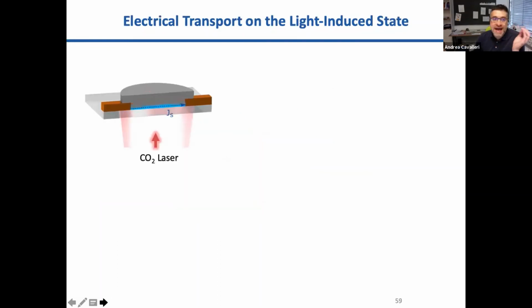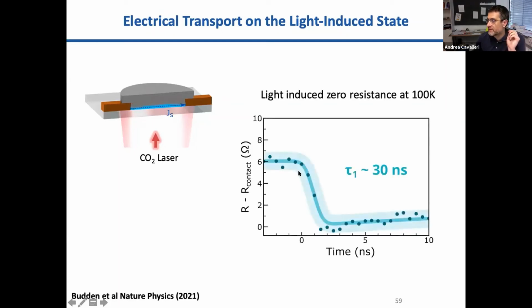So things that we're doing now, of course, now that we have longer-lived superconducting-like states, we have measured resistivity using 2 probes, and we could show that at least with 2 terminal measurements, which require some calibration, the resistivity of this light-induced state is compatible with 0 resistivity. It drops, if you're careful, by 2 or 3 orders of magnitude at least, and stays low for about 10 to 30 nanoseconds, depending on how you fit the data.